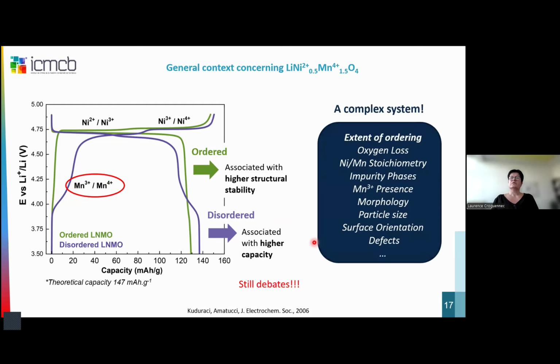So as mentioned, it is still a complex system, considering especially that all these are highly correlated. The oxygen loss we have during the thermal treatment will control the nickel over manganese stoichiometry in the active phase, considering that, of course, the stoichiometry of nickel over manganese in the compound does not change. But depending on whether we have impurity or not next to the active phase, we can have a very different stoichiometry in the active phase and very different impurities next to it. And depending also on the stoichiometry, we have, as just mentioned, the presence of manganese 3 plus.